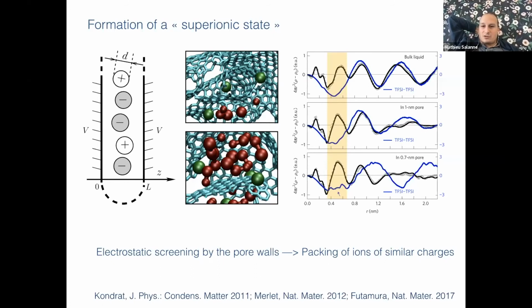So these are the ones you have on the right. And in fact, if you look at the yellow region, this is anion-anion correlation. And what happens is that you have the blue signal, which starts to show some pre-peak at the bottom. And by doing reverse Monte Carlo, it was shown that this really corresponds to the superionic state first predicted by Kornyshev. So I think this is a very good example of theory confirmed by simulation, then confirmed by experiments in order to interpret a physical result.